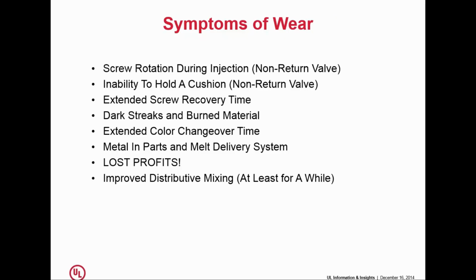Now, ironically, one of the things that happens when you start getting wear is you may actually see better distributed mixing, because with wear comes this random process of the material not feeding forward as efficiently as it might. And so very often, you'll hear people complain, well, I just put a new screw in and I'm getting worse mixing than I did before. Well, that's because now the material is moving forward the way it's supposed to, and the true limitations of your system are now exposed.